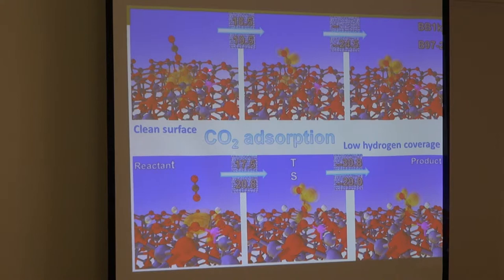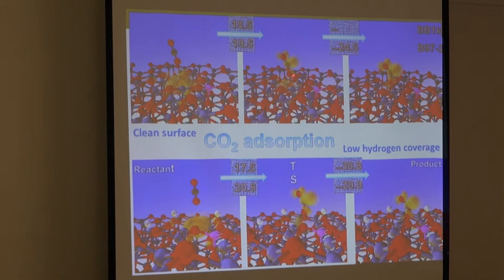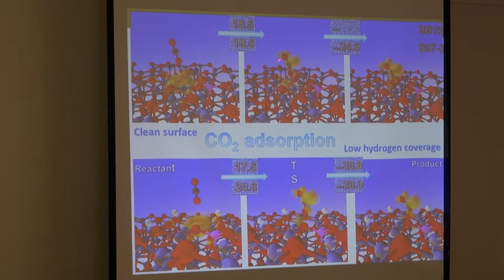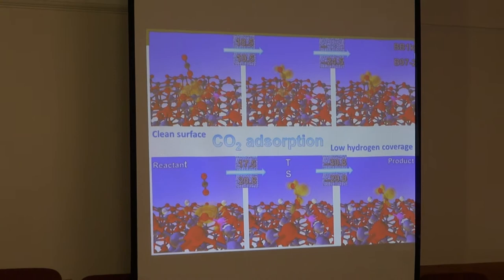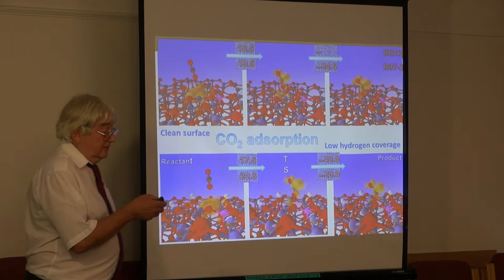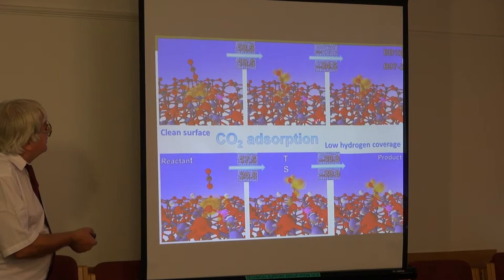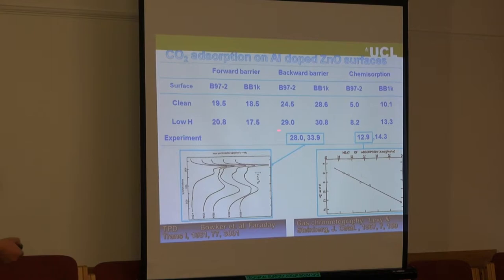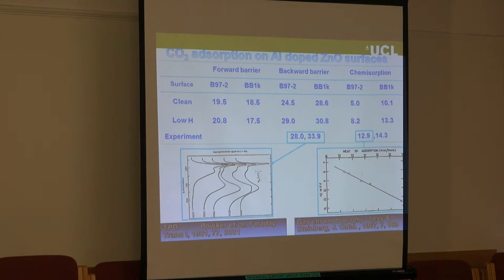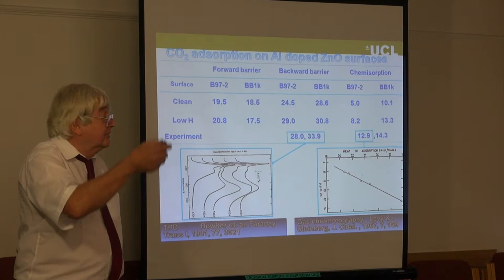This is, I think, part of an important general mechanism in CO2 chemistry — how we can activate CO2 using electron donor sites on the surface. Again, comparing with Bowker's TPD data for CO2 shows really nice agreement between calculations and experiment. That was the first example from catalysis, showing that this electron trapped at the surface acts as a defect and is crucial to the catalytic process. Trapped electrons on oxide surfaces are probably important in several other areas of catalysis.